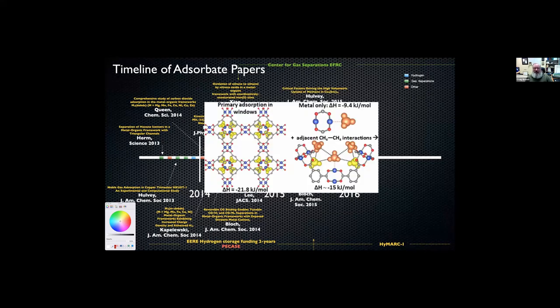So Eric did some nice work looking at metal organic frameworks in HKUST-1 in collaboration with Bess, a theorist who was working with Martin Head-Gordon and the people out at Berkeley. They computed that the methane within those octahedral cubes, away from the transition metals, are the most stable adsorption sites. And it's really the interaction of different methanes across the pore between the different paddle wheels and the copper interaction that sums up to get almost 15 kilojoules per mole enthalpy for interaction. The methane really doesn't like the metal center in that case. I guess it's a bit too bulky to interact just on its own.